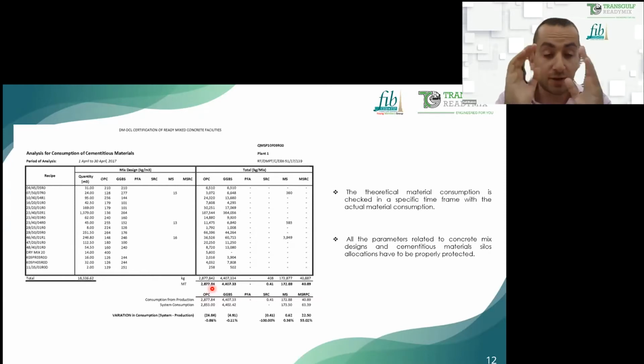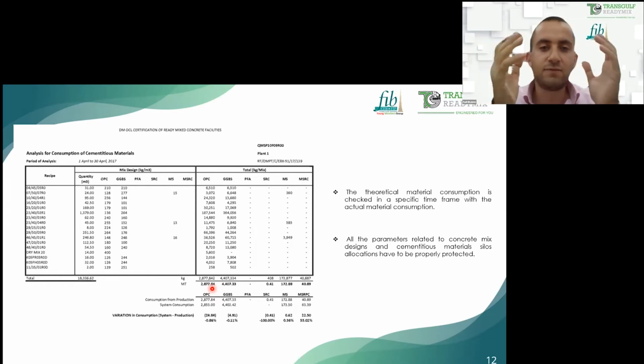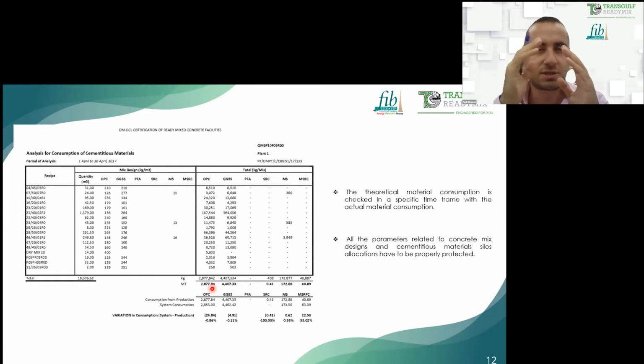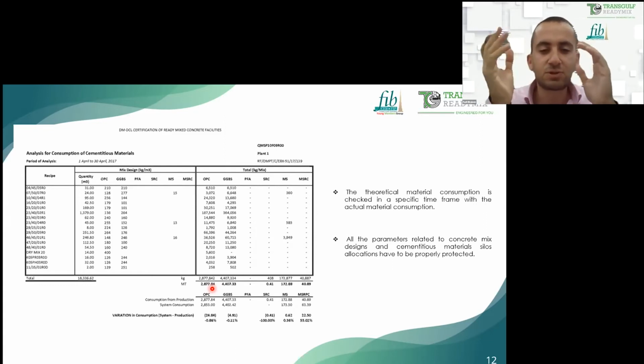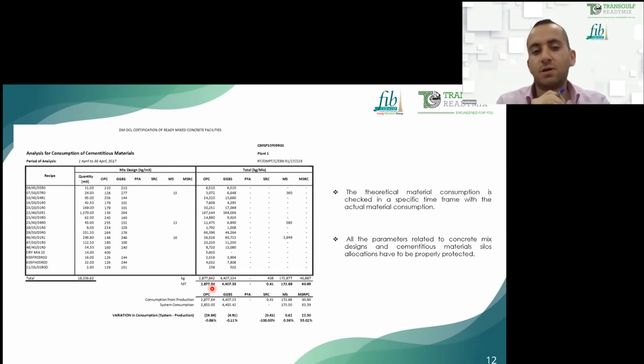Another parameter generated from the system is the actual consumption. So how much actual OPC was consumed, and how much actual GGBS was consumed. So we verify the theoretical versus the actual, and the variation limit is related to the scales' accuracy. As an example, for the cement, it should be within plus or minus 1% for the variation.